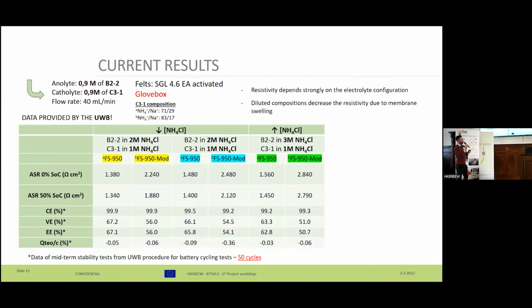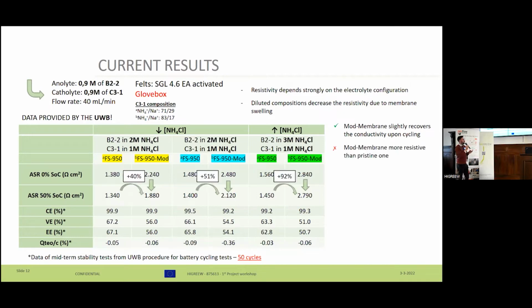So going into more detail with this data, what we can see is that upon cycling our modified membrane version slightly recovers the ion conductivity, and this means that our membrane needs a small period of activation, and even more if the membrane is assembled in the dry state form. Yes, this is a fact that our modified membrane is more resistive than the pristine one, but as I was talking about, depending on the electrolyte configuration, we have different behaviors.